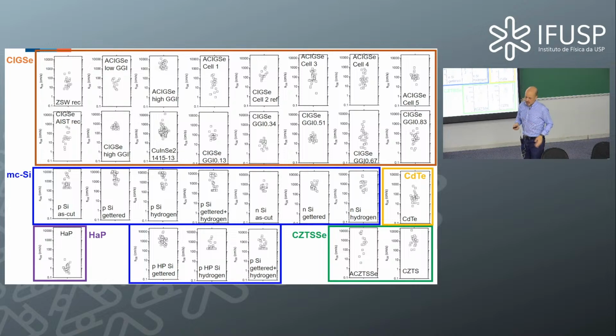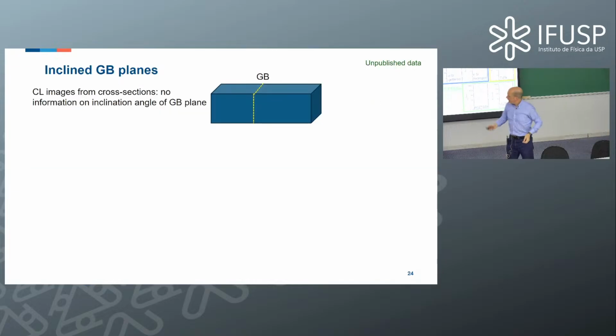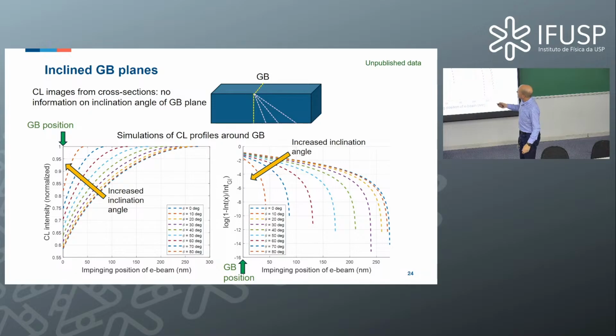I will show you the model in a moment, but when we discussed with a collaboration partner, one colleague said, but you know, the grain boundary actually is not oriented like this, right? We see some line in our cross-section, but how is it oriented in this? Do we know? We cannot detect it, right? So maybe what we see is only an effect of the geometry of the grain boundary. So of course it means that we have to simulate profiles. And yes, there is a strong effect of the inclination angle on the grain boundary profile. But what we can determine and confirm is that the recombination velocity is completely independent of the inclination angle, completely. So this is not an issue.